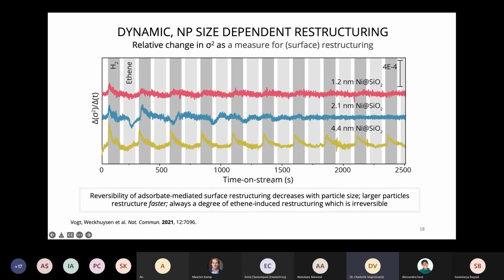If we take those 70,000 spectra and we fit all of them using FEFFIT for the Debye-Waller factor, and again, for this experiment, all other things being equal, that can be a measure for the amount of relative surface restructuring, and we take the derivative of that Debye-Waller factor, we plot that against time, then we're able to obtain information about the reaction kinetics, or about the restructuring kinetics of the nanoparticles in these different pulses.